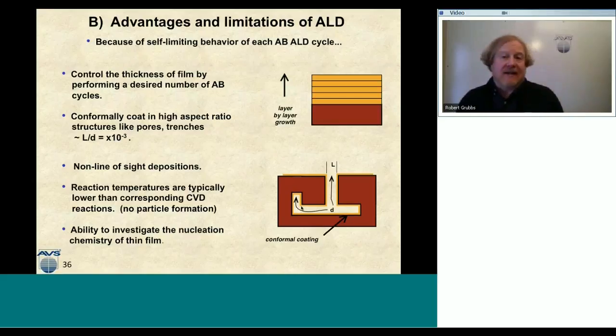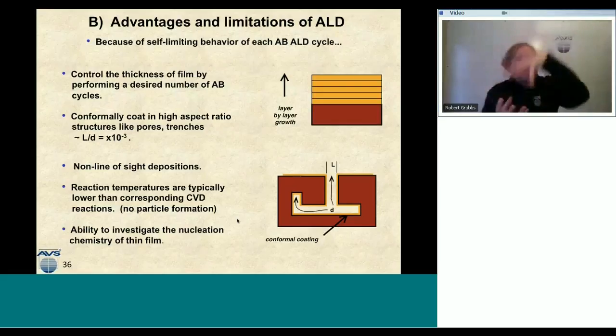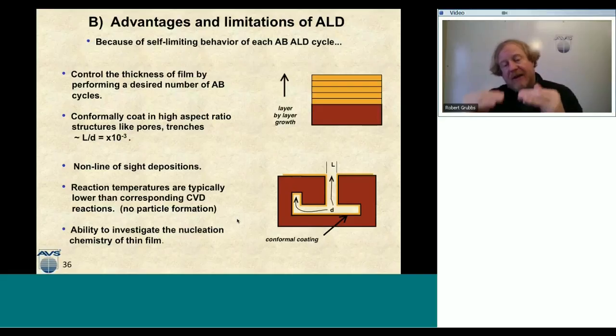The last advantage that I see in ALD chemistry is the ability to investigate the nucleation of a thin film. Now, the other deposition techniques, they just came down and sputtered the film, or deposited relatively rapidly. But because ALD is doing this stepwise, one half cycle at a time, you can watch a surface physically evolve from what the substrate was into the deposited film. And I think that's a very powerful technique, because as devices get smaller and smaller and interfaces become more and more important, we're really going to need to understand what those interfaces are, and those interfaces are really what happens as a film nucleates on top of another film.